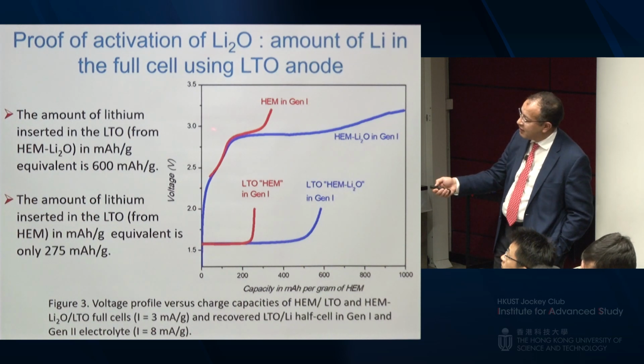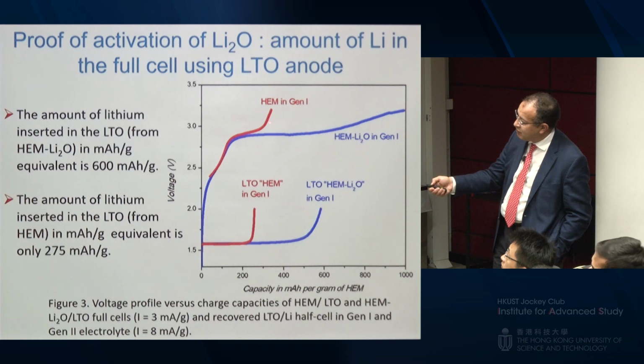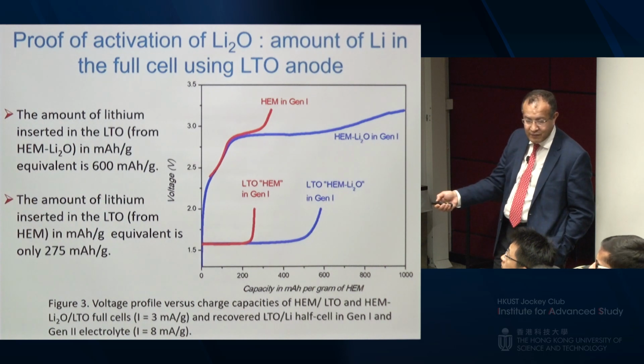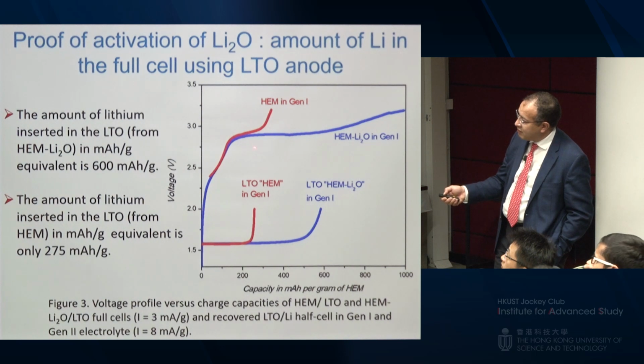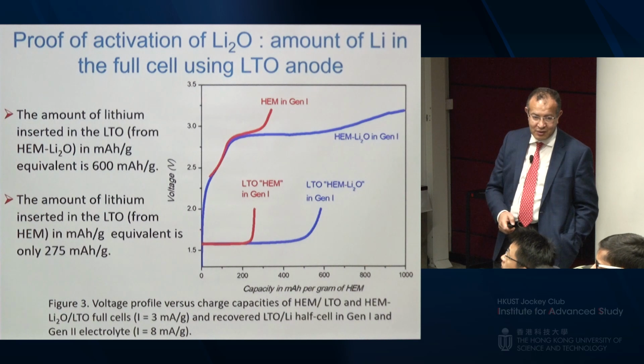For example, in the case of high energy cathode, you can design LTO to match it, and you get about 250. That's the capacity of the cathode. So if you add 1% of lithium, you can see there is a huge capacity, and you recover it at the LTO, which means that lithium really comes from that lithium.